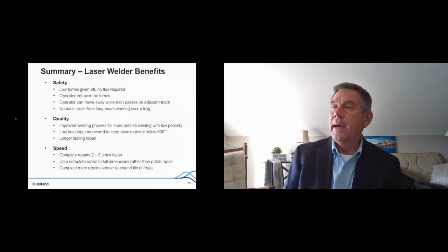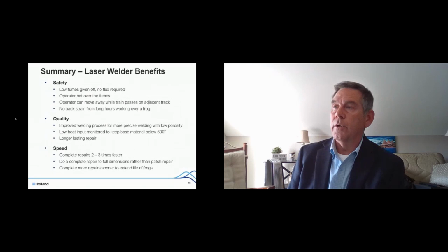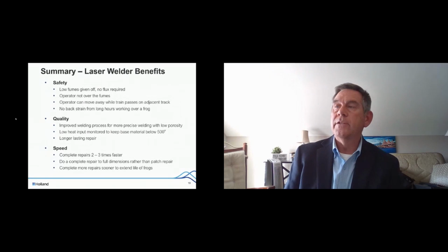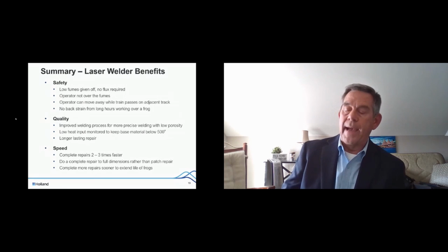So in summary, I can indicate that the laser welder has various benefits. First, obviously safety. Low fumes are given off. No flux is used, so you don't have the fumes from the flux, and you actually use less material for the same repair. The operator isn't bending over, breathing in the fumes. The operator can also get up and move out of the way with a passing train on an adjacent track and is not leaning over all day long with back strain.